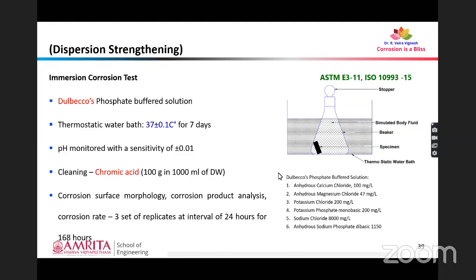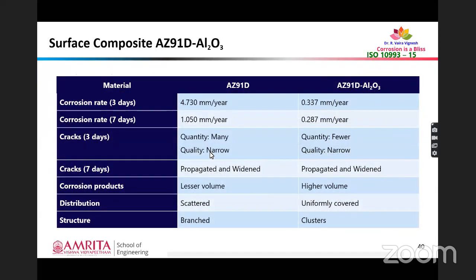And after a period of 24 hours, we have taken the specimen out, dried it, and cleaned it using chromic acid, prepared with 100 grams of chromium oxide in 1000 ml of distilled water. Then we have determined the corrosion rate of these specimens. This was done in triplicate at an interval of 24 hours for a period of 168 hours. That means we have repeated the same steps for 7 days. Based on our analysis, here is the result of corrosion rate after 3 days and 7 days of immersion.